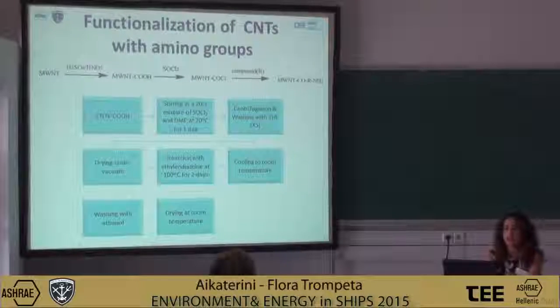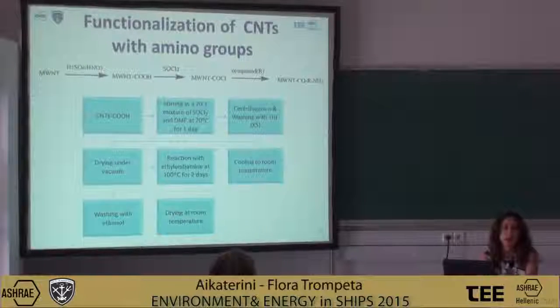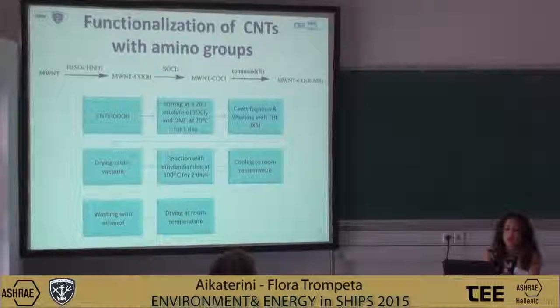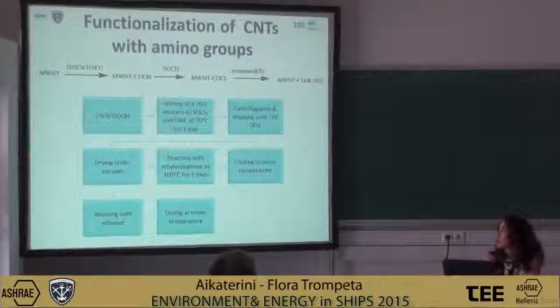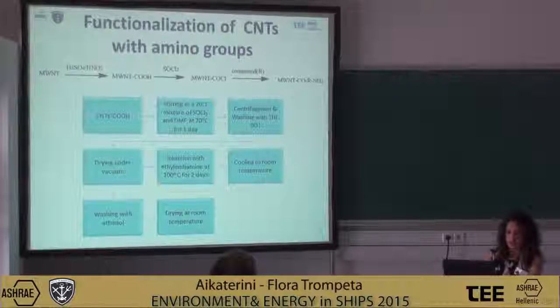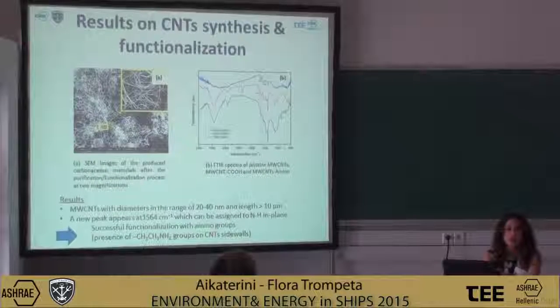The other functionalization that took place was the functionalization with the amino groups, in which we used the already synthesized carboxyl CNTs, with the carboxyl group, and we tried to add an amino group, an amine, using thionyl chloride and this procedure. The critical step in this reaction was the addition of ethylenediamine at 100 Celsius for 2 days. The results of the functionalization can be observed by the FTIR spectra, in which we can observe a new